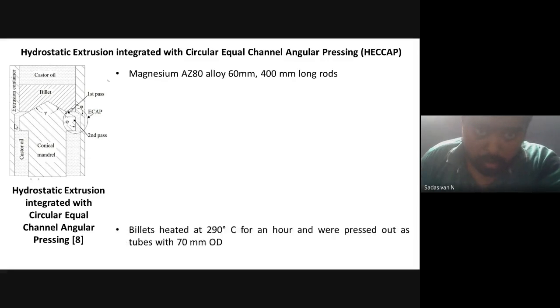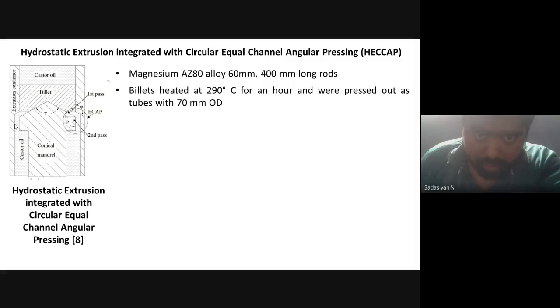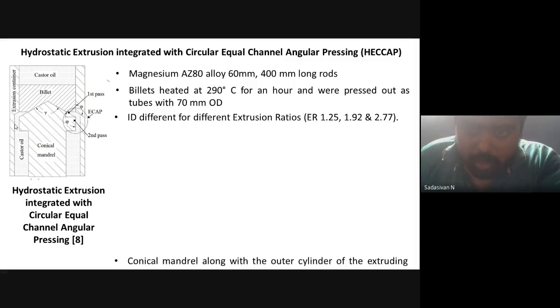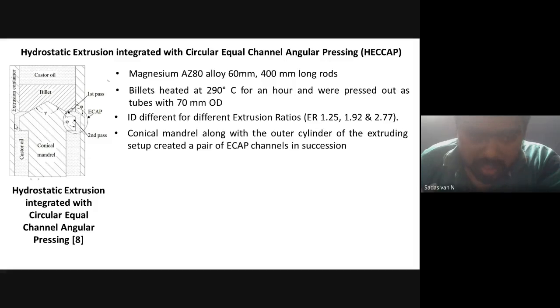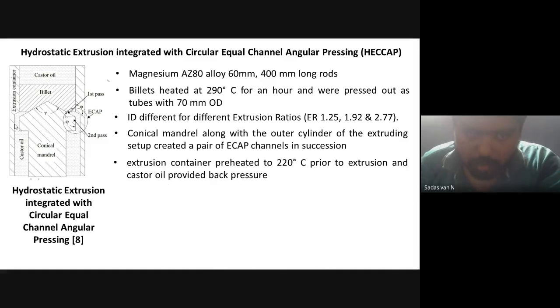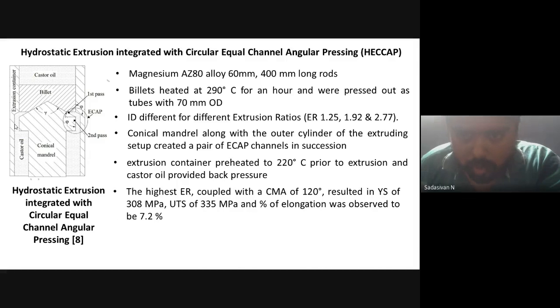Outward flow ECAP, with reverse hydrostatic back pressure, was applied on magnesium AZ80 alloy. 60 mm billets of 400 mm length were taken, and the billet was formed at 290 degrees Celsius forming temperature, because magnesium is brittle and it's difficult to form it at room temperature. Three different extrusion ratios were used, bringing out tubes of the same outer diameter but different inner diameters. A conical mandrel was used to create the obstruction for extrusion of the tube. The extrusion container was maintained at 220 degrees Celsius to avoid chilling at the die contact surface.